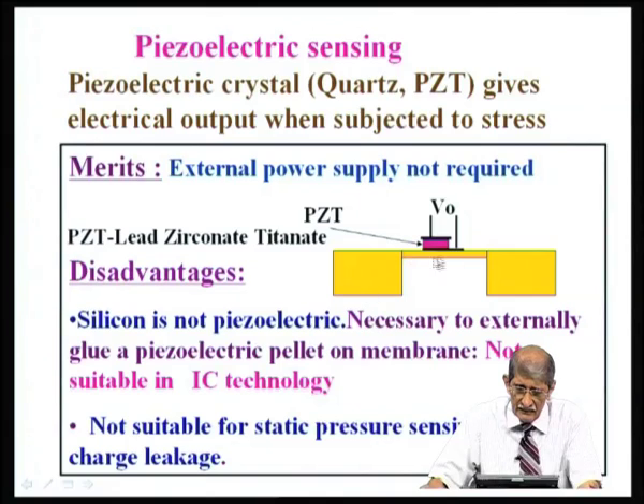Okay. But the problem is, this PZT has to be glued externally onto the membrane. The pellet is glued onto this, and this is not part of the conventional integrated circuit technology. Still, you may say I can deposit some PZT polycrystalline materials and use it, but then the sensitivity will go down if you use such materials. But a more serious disadvantage is it is not suitable for static pressure, because if you have static pressure, the membrane deflection is constantly there and the strain is constantly there, and constantly the charge developed across this piezoelectric crystal will be leaking. It is like a capacitor being charged, the capacitor charge will leak.